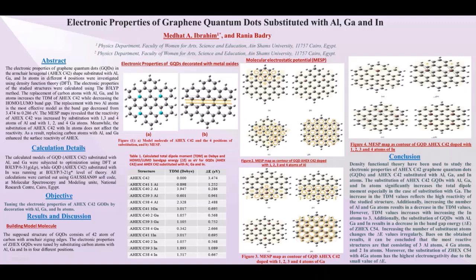Building model molecules, the supposed structures of graphene quantum dots consist of 42 atoms of carbon with armchair zigzag edges. The electronic properties of armchair hexagonal graphene quantum dots were tuned by substitution with the aluminum, gallium, and indium atoms in 4 different positions. The results indicated that the electronic properties of graphene quantum dots in the armchair hexagonal shape substituted with aluminum, gallium, indium atoms in the 4 different positions were investigated successfully using density functional theory.